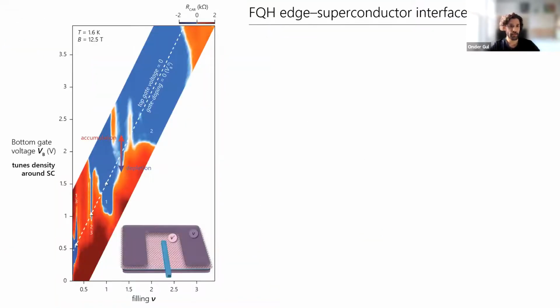Next, we investigate the graphene-superconductor interface. The top graphite gate is carved out by around 100 nanometers to prevent an electrical connection to the superconductor, whereas the bottom gate is continuous, so it covers all around, and is separated from the superconductor by the bottom boron nitride. The combination of top and bottom gates allows for tuning the density around this 100 nanometer region around the superconductor without affecting the filling in the bulk away from the region. Basically, this region is encapsulated by both gates.